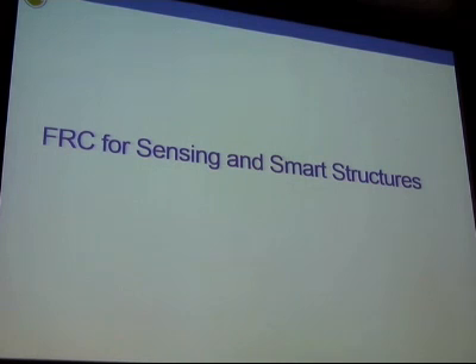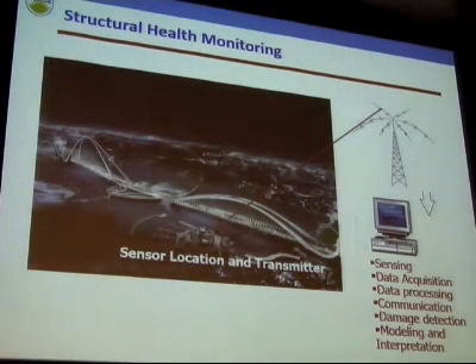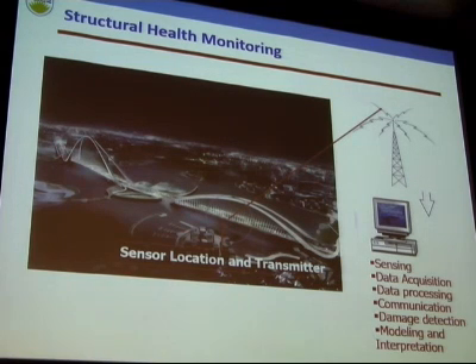When you have these structures which are highly deteriorated, how do we actually create a scenario where these structures can talk back to us? And when the structures can talk back to us, you can essentially understand what the condition is and how far we are from approaching a certain collapse state. So in other words, what we're looking at is putting sensors on these structures. So you have this typical bridge. You can put certain sensors on it which can then correspond or interact with us over the internet.